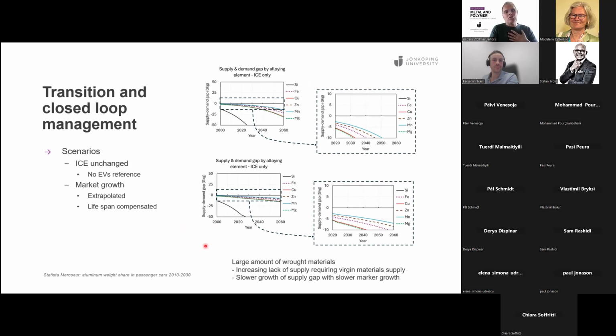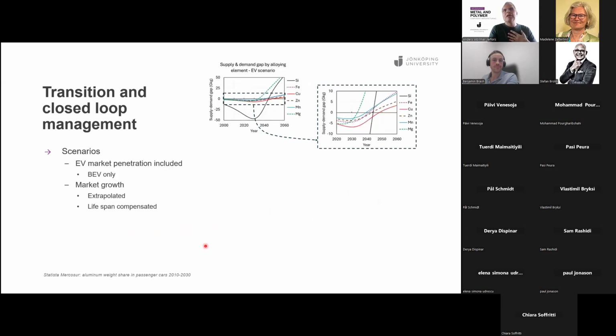So now the consequence is, if we take the electric vehicles with the very low silicon content, that means that for the scrap coming back from the old cars, the silicon will turn, at about 2030 sometime, and it will start to go up, and there will be a surplus of silicon. Now, if we look a little bit more in detail here, we can see that the first material that will be coming in excess is the magnesium. And then we have manganese, and there is also iron and so forth, with copper being the last one.